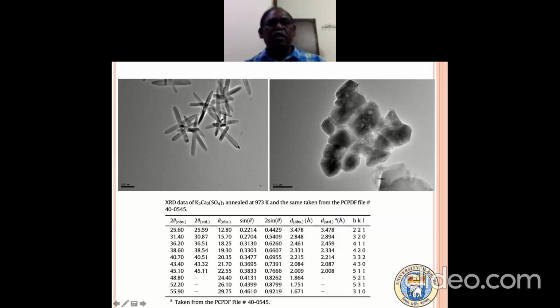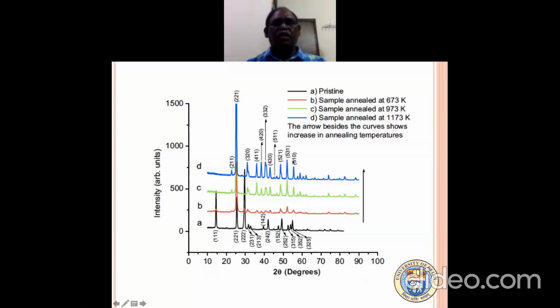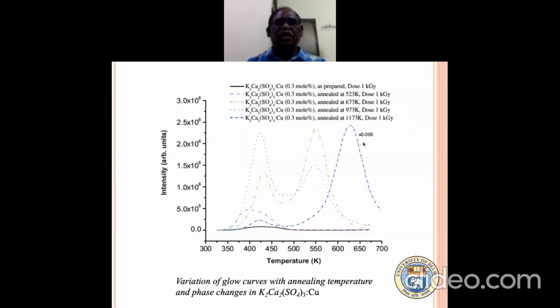The nanorods also break, because the initial phase is orthorhombic, and when you anneal, it goes to the cubic phase, and therefore there is stress, and these nanoparticles break also. The XRD pattern shows this in orthorhombic and this in cubic form. So there is a phase change, and with it all the glow curve structures also change. This study is very important, because using the area under the curve or the peak height, we determine the radiation doses, so any change matters, and we also heat and cool this material several times while reusing it.